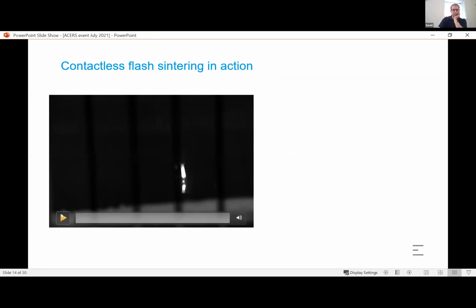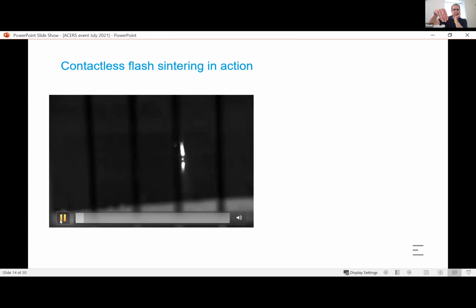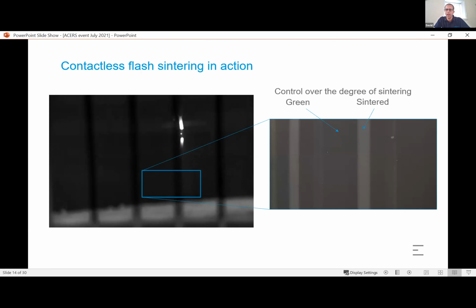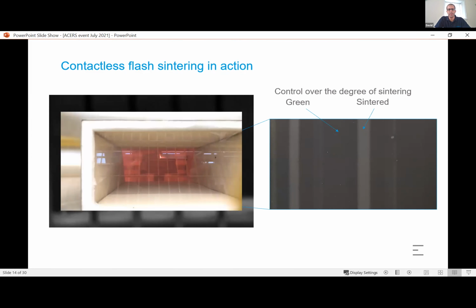Forgive me, I'm skipping through some slides here just so I don't overrun and frustrate everyone. But here it is in action. So this is I guess the main interesting bit. Here you're seeing a metal base with a solid state electrolyte layer printed on top, and this is a very simple electrode setup, but we're rastering an electrode over the top. And this is precisely to increase the productivity and reduce the amount of time it takes to sinter these multi-layered materials, or indeed these solid state electrolytes. So you can clearly see sintered layers next to still green layers there that we're looking at. And indeed, this is just a picture of what you're seeing, where we're rastering in a different direction.